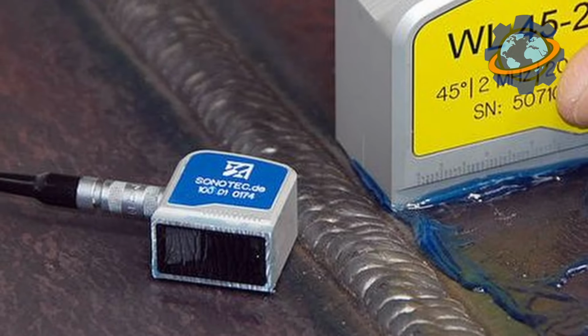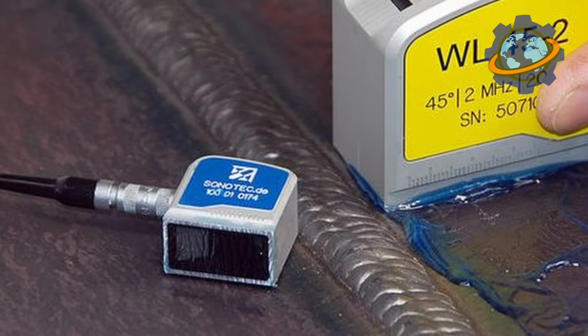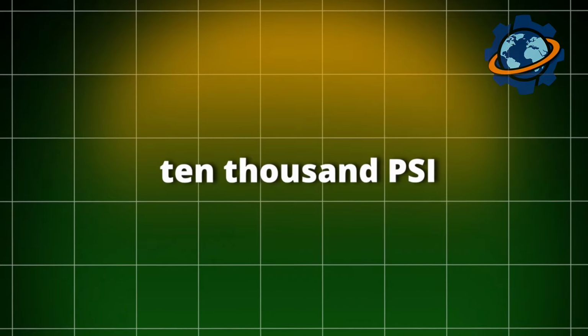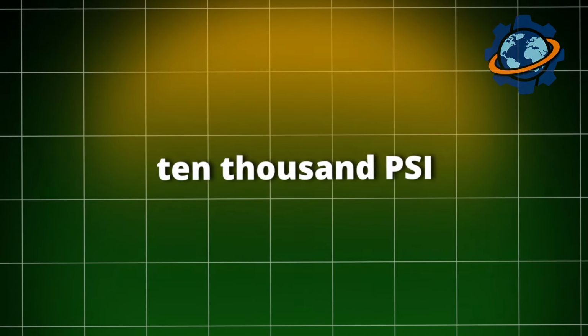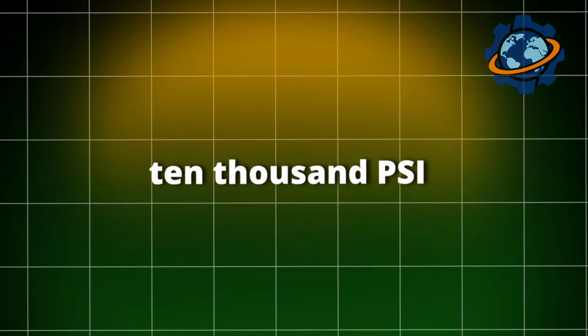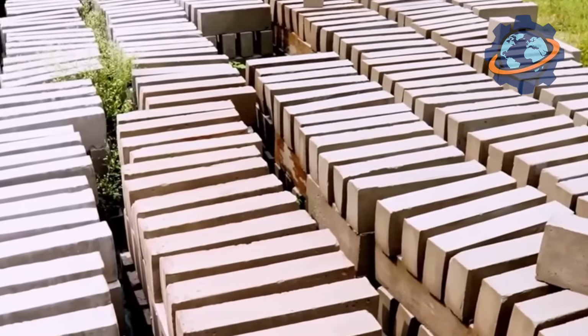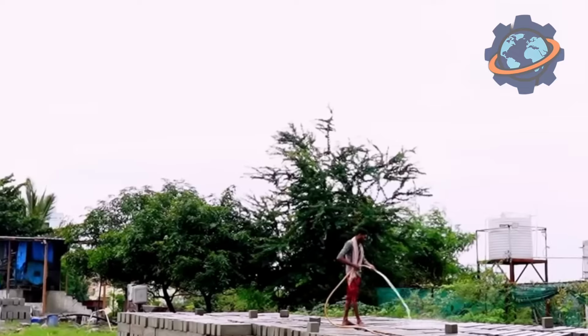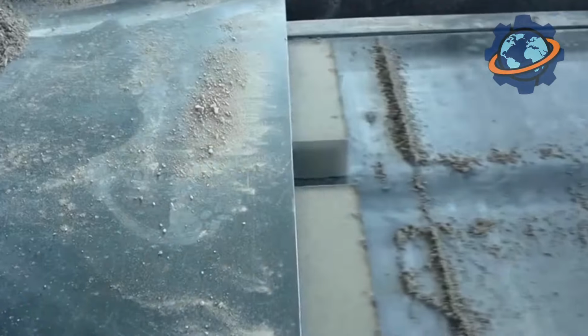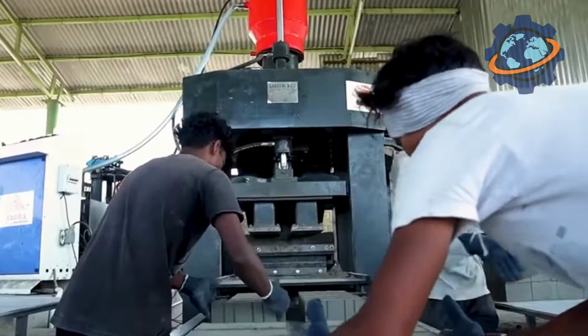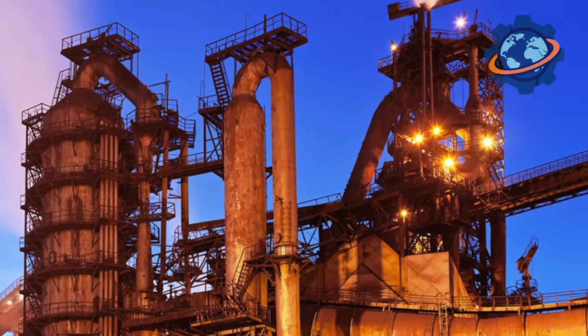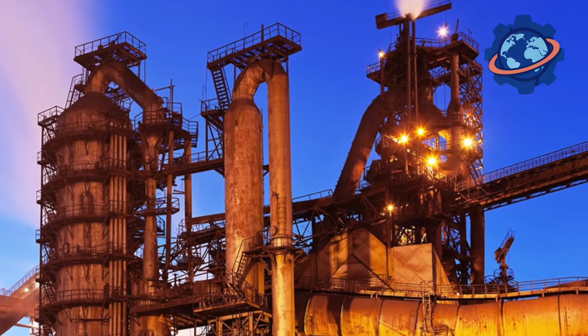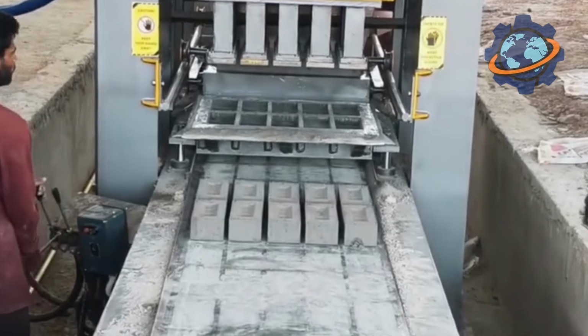But sound testing is just the start. Samples get crushed in hydraulic presses, measuring compressive strength exceeding 10,000 psi. Others get thermal shocked, heated to 2,000 degrees, then water quenched. Survivors prove they'll handle the brutal thermal cycling of industrial furnaces. Failure rate must stay below 0.5%. Even one weak brick can collapse a furnace wall, causing million-dollar shutdowns.